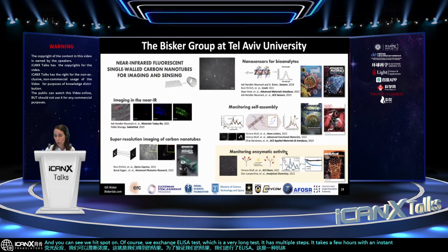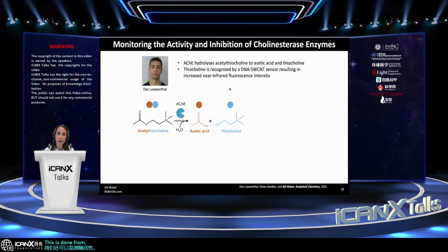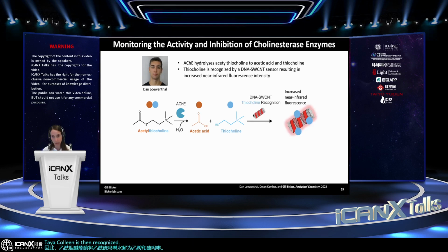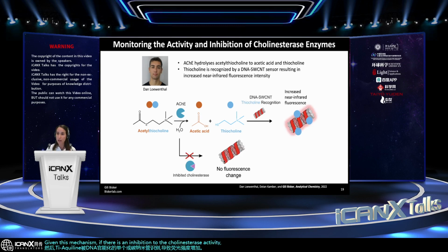We can also monitor enzymatic activity. This is done from my group, and we were aiming to detect the activity and inhibition of cholinesterase enzymes. So acetylcholine esterase hydrolyzes acetylthiocholine, this molecule, to acetic acid and thiocholine. Thiocholine is then recognized by DNA functionalized single-wall carbon nanotubes, resulting in an increase in the fluorescence intensity. Given this mechanism, if there is an inhibition to the cholinesterase activity, then we would see no fluorescent response.